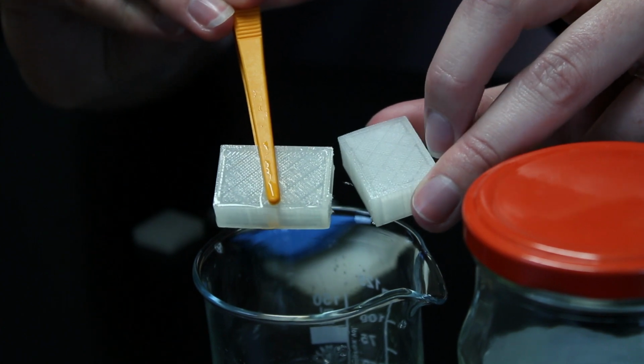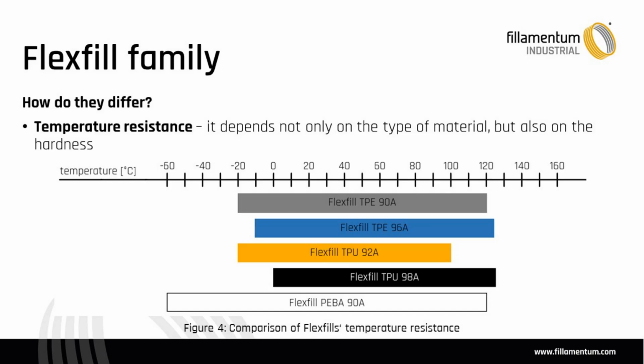just became more transparent. When we have a look at the temperature resistance, it doesn't depend only on the type of the material, which is TPE, TPU or PEBA, but it also very much depends on the hardness. It can be seen in the picture. For example, comparing TPE in two hardnesses, we can see that the range of temperatures where it resists is from -20, -10 degrees up to 120 or 125 degrees. And it's related to the hardness of the material.